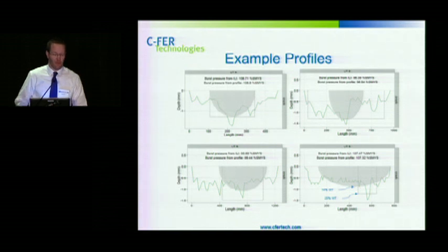On the top right, we have one where the ILI tool found most of the feature, most of the length, and had a very close depth call. On the bottom left, we have one where the depth call by the ILI tool was deeper than what was found in the field. And so again, that results in a conservative estimate.